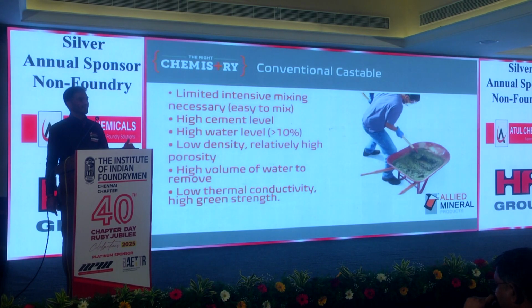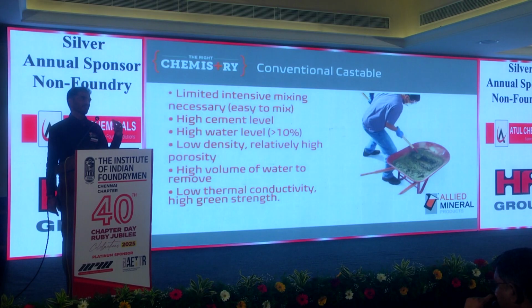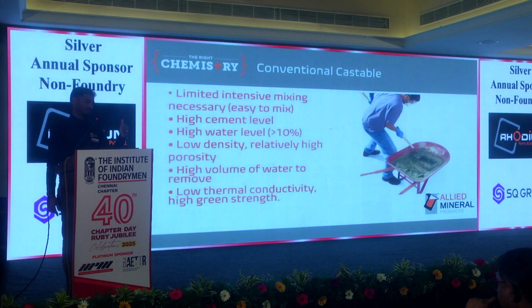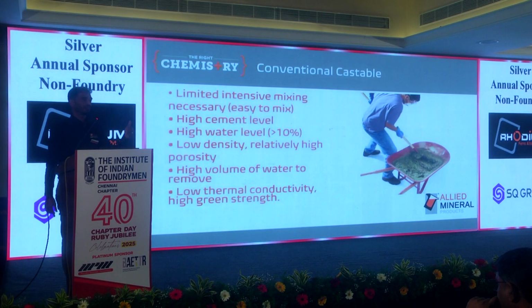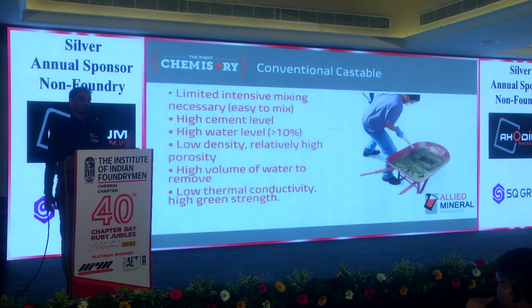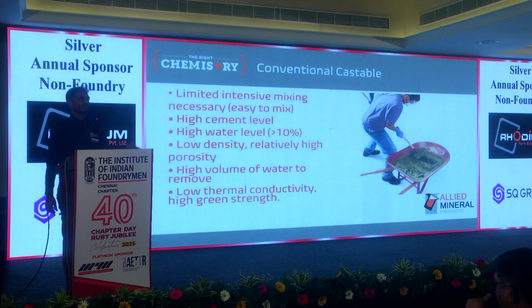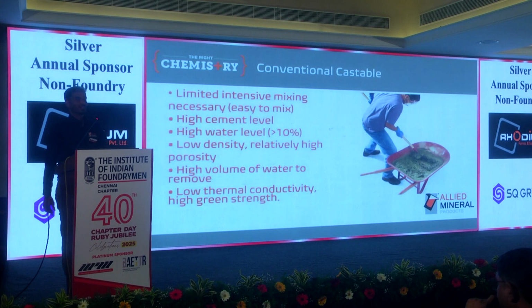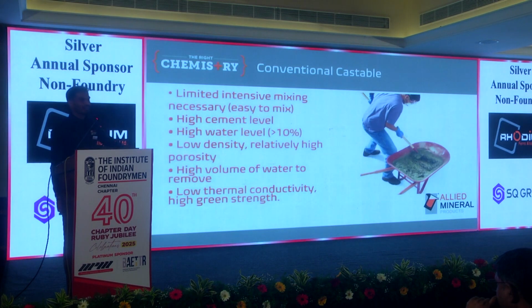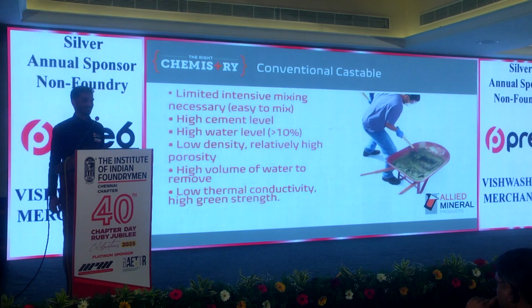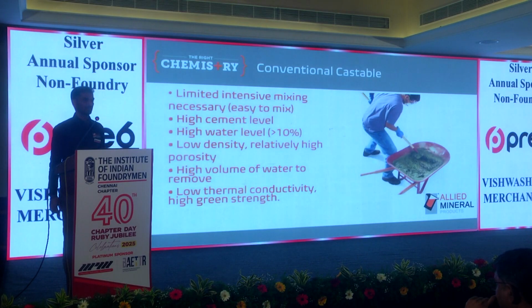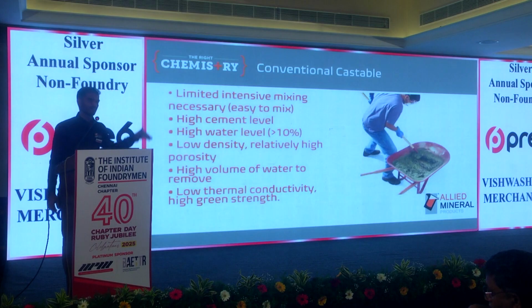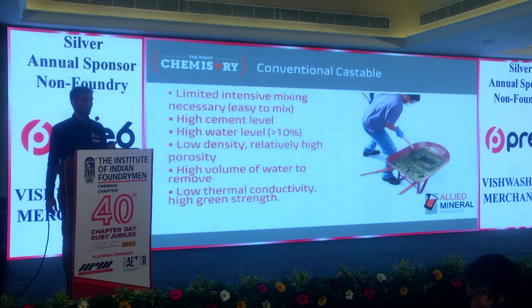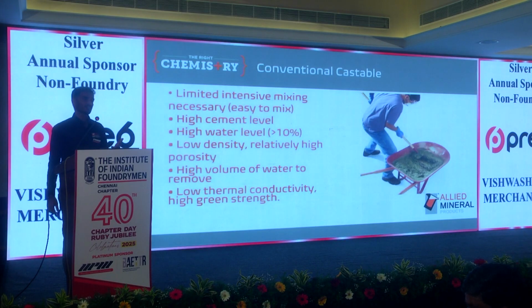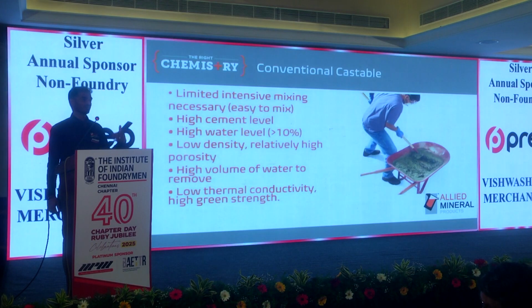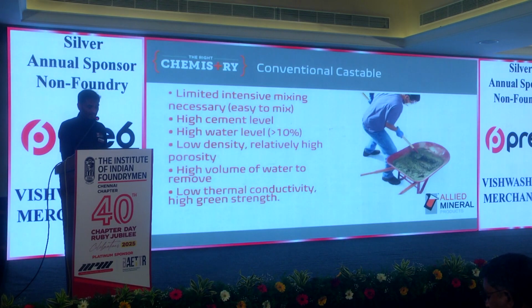And here I would like to make the point that people are moving from sand, CO2 sand, whatever we were using in the past, towards castables. So that means you need to have proper refractory mixes also. You can't do a low cement castable or no cement castable just by hand mixing. You need to have a proper mixer. To get the proper performance of any castable you are talking about, you need a proper mixer, and the proper water percentage has to be maintained so as to get the proper properties of the material.